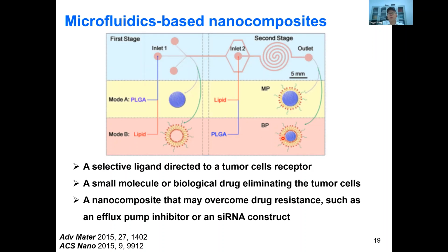So when we have the PLGA within a layer of water and another layer of liposome, then we have a lot of water between these two layers. So that's a soft particle. And when we directly coat the surface of the PLGA with a liposome, there's no water in between. We can do this particle fabrication very easily with a channel.